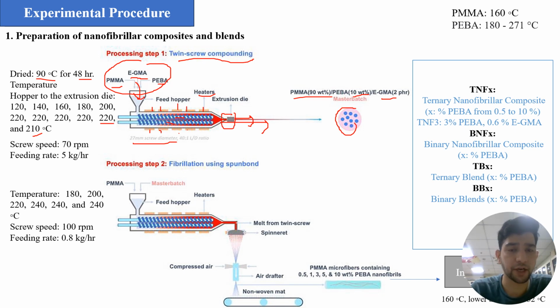So in the first step he tried to make a master batch. In the master batch, the concentrations of PMMA, PEBA and EGMA are different, and this concentration can be controlled from here. So he made the master batch, and when the author added the sample here, the screw rotates at a certain rotation speed, which is called RPM. The speed of the screw is 70 RPM and the feeding rate is 5 kg per hour.